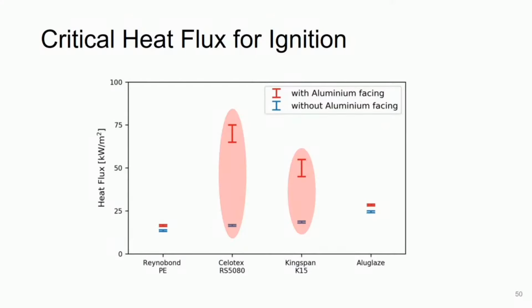However, the ignition behavior of the polymer foam insulation products, Celotex RS5080 and Kingspan K15, is drastically affected by removal of the foil facers. Again, red with the foil facers and blue without. These products are both much more difficult to ignite when their foil facers are present, as we should expect. The foil facers reflect radiation, they alter the convective heat transfer conditions at the surface of the samples, and to some extent, they mitigate ignition and burning of the flammable pyrolysis products that are generated during heating.